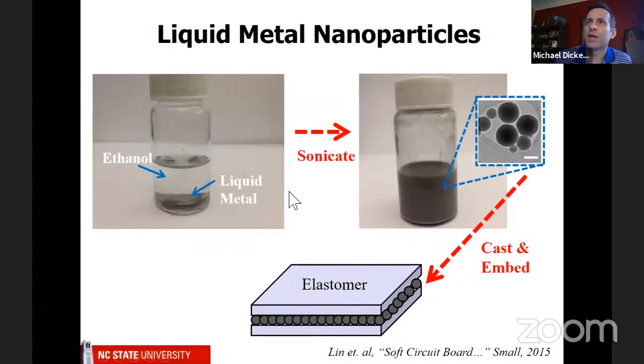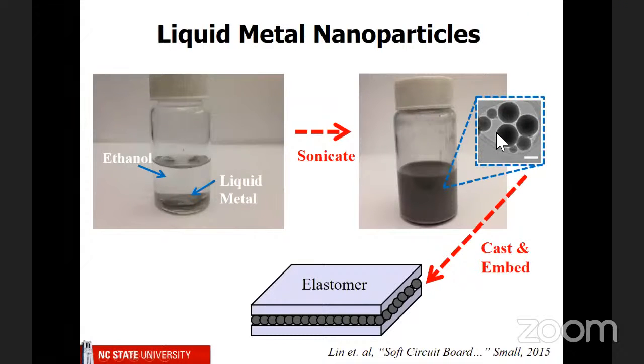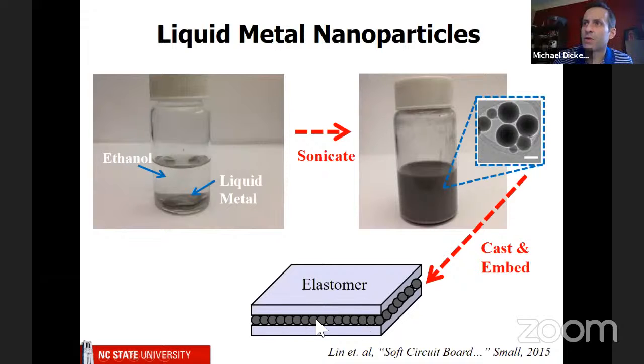Okay, so we've taken these. This is a picture of an actual vial of ethanol with the liquid metal, and we sonicate it, and we get the very small particles. Again, this is what they look like. And the idea that we had initially was, well, what if we cast a film of these? Then we could actually make a conductor out of this. But the problem is actually it's not a very good conductor because the electrons have to jump from here to here to here to here, just jump, jump, jump, jump. And it's not a good conductor at all.